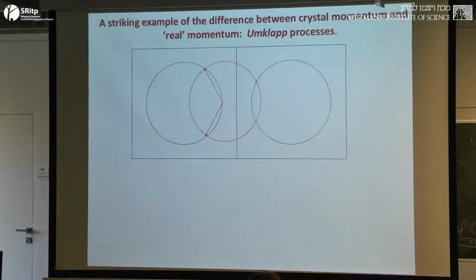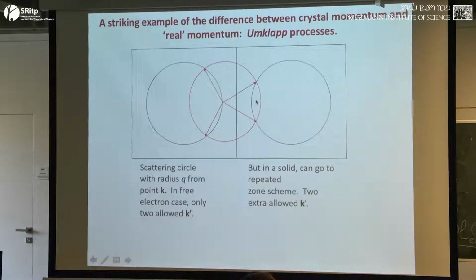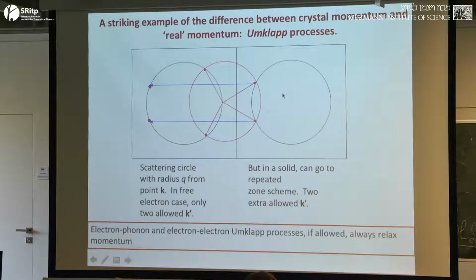And actually, there will be a Brillouin zone next door, and the Fermi surface can equally well be defined in the next door Brillouin zone, which means that your scattering circle also intersects a perfectly respectable Fermi surface there, which means that instead of there being 2 final states those electrons could go to, there are 4. Those ones get umklapp back with a reciprocal lattice vector. So those umklapp processes are equivalent to that scattering center there being able to scatter you right across the other side of the Fermi surface.